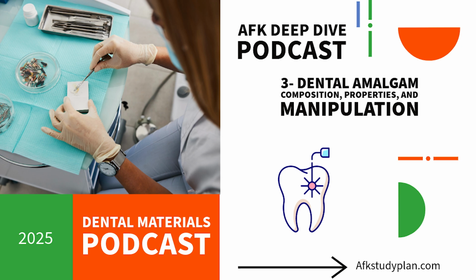Okay, let's try and wrap this up. This deep dive really showed that dental amalgam is way more than just a simple silver filling. Absolutely. It's a carefully engineered alloy. Mercury's role is complex, but vital. And the specific metals, especially getting that high copper content to kill off gamma-2, make a huge difference. Huge difference in performance, yeah. Less creep, less corrosion. And the dentist's technique, mixing, packing, carving, polishing, every step, is just critical for success.